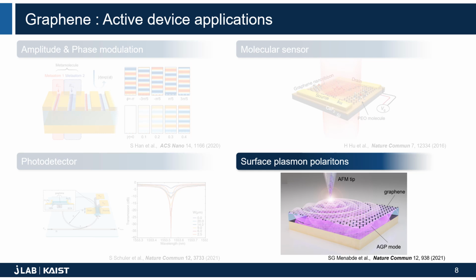This paper, published in Nature Communications in 2021, was the first to image the acoustic plasmon mode in a graphene-dielectric-metal structure. It resulted from the coupling of graphene plasmons with the mirror image in the metal reflective layer below, and the use of a sub-nanometer thick dielectric allowed for very high electric field confinement.